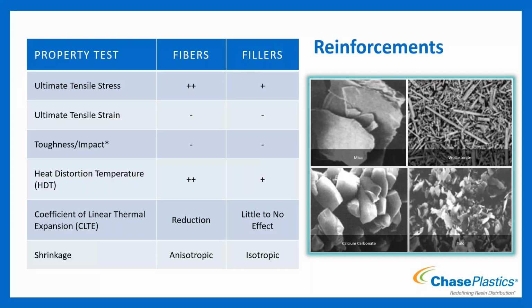And then your HDT, your thermal performance, you're going to see a boost when you add glass. So the thing there is your stiffness and strength gets higher, you lose your impact and tensile elongation, and you see an increase in thermal performance. You'll typically see a reduction in thermal expansion - the glass doesn't really want to move.